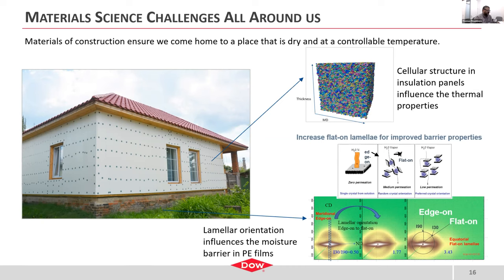If you look at the thermal insulation on the outside of your house, it's often either a polystyrene or a polyurethane or polyisocyanurate foam panel. The reason foam panels are used as thermal insulation is because they affect the thermal conductivity in three ways. First, the cellular nature of the material provides a low density, and that low density reduces the thermal conduction of the solid material between as the heat wave propagates.